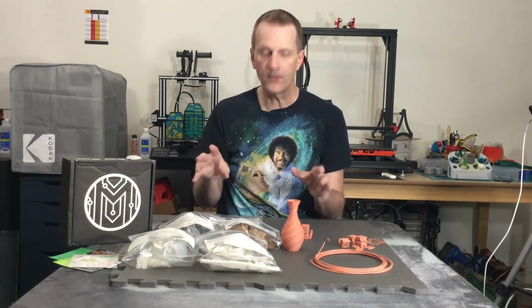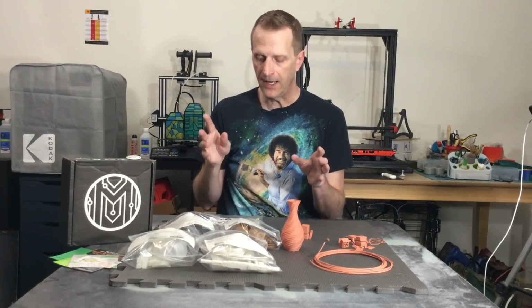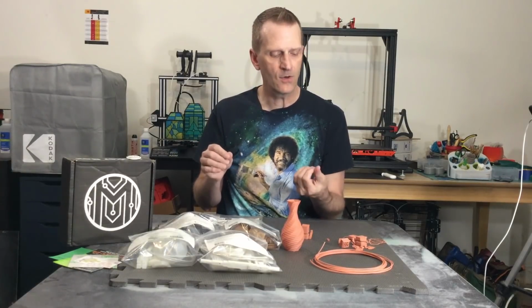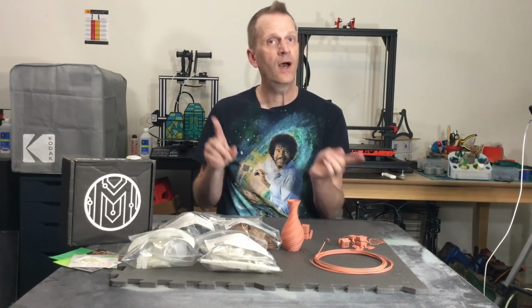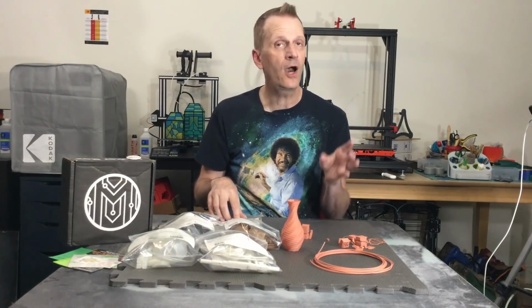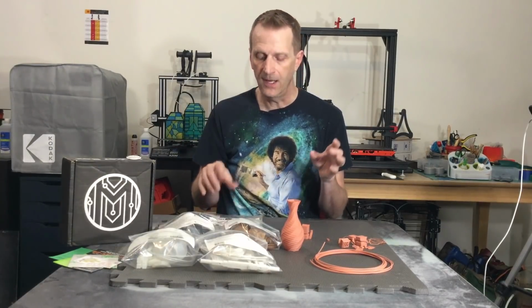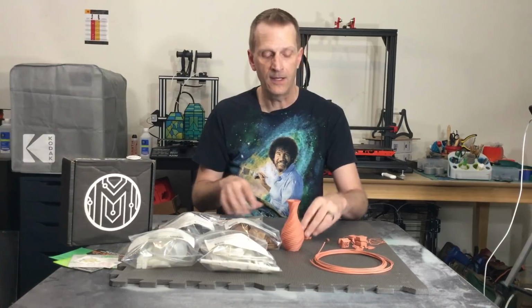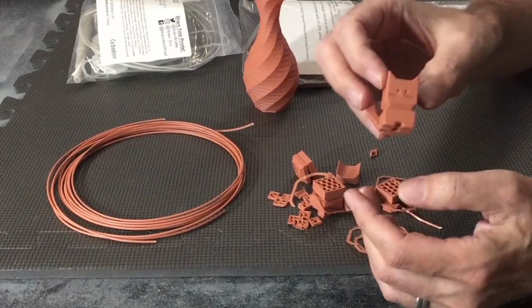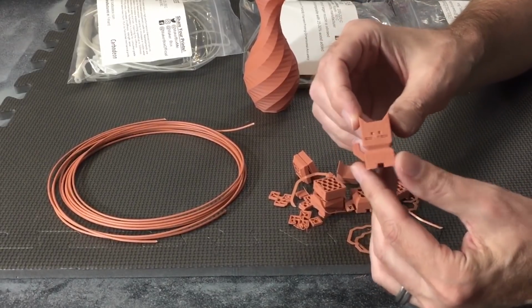We're now at 200 to 230 C and 95 on the bed. So the next step was to go hotter. So we went to 240 C on the hot end and 105 C on the bed. And I was able to get out a successful print. There was no interlayer warping.